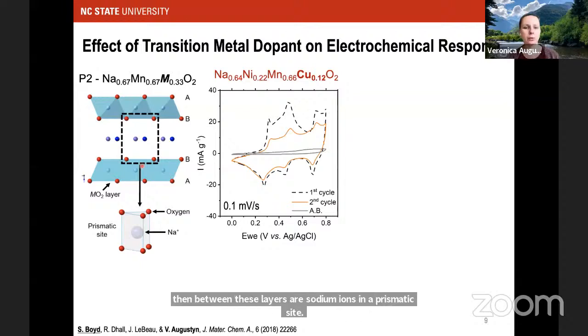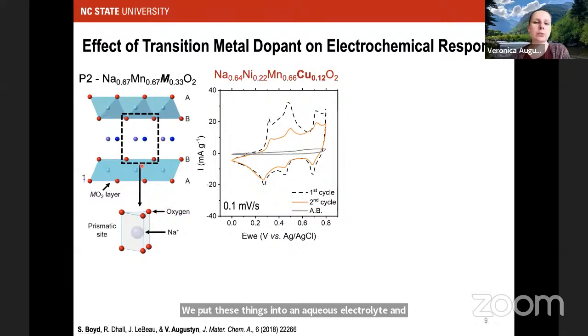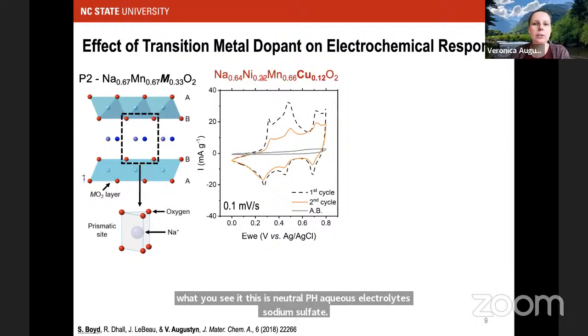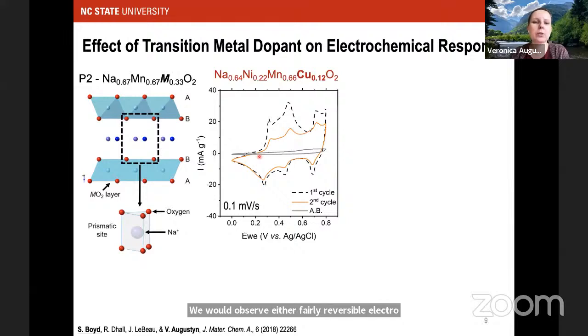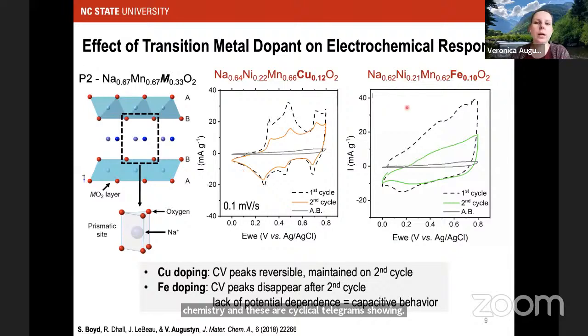We put these things into an aqueous electrolyte, and this is neutral pH aqueous electrolyte, sodium sulfate. What we observed is that depending on the exact transition metal composition, we would observe either fairly reversible electrochemistry, and these are cyclic voltammograms showing sodium deinsertion and insertion into the material, or if we just slightly change the composition, we would see very different cyclic voltammetry, where the peaks would disappear with cycling fairly quickly, become featureless in terms of any specific potential dependence, and look very capacitive.